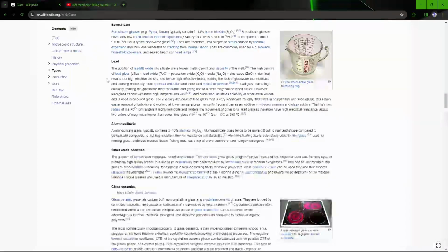Lead oxide also facilitates solubility of other metal oxides and is used in colored glass. The viscosity decrease of lead glass melt is very significant, roughly 100 times in comparison with soda glass. This allows easy removal of bubbles and working at low temperatures, hence its frequent use as an additive in vitreous enamels and glass solders. The high ionic radius of the Pb2+ ion renders it highly immobile and hinders the movement of other ions. Lead glasses therefore have a high electrical resistance, about 2 orders of magnitude higher than soda glass. A Pyrex borosilicate glass measuring cup.